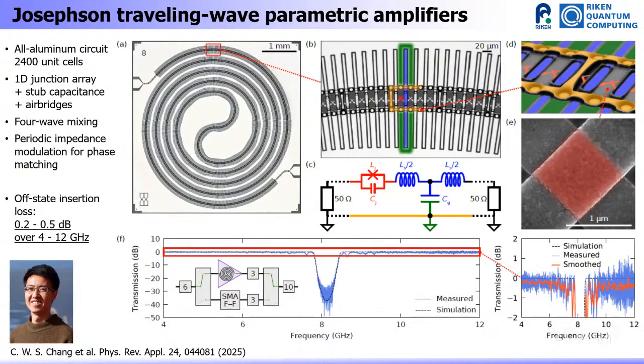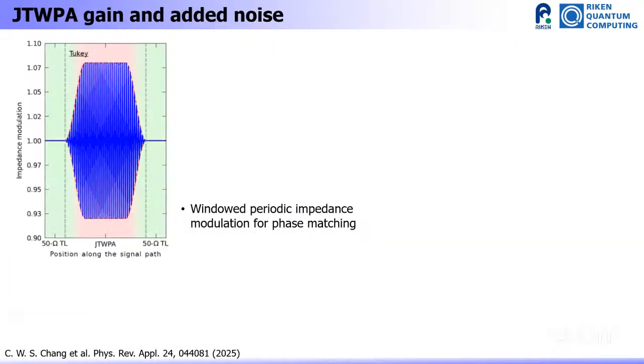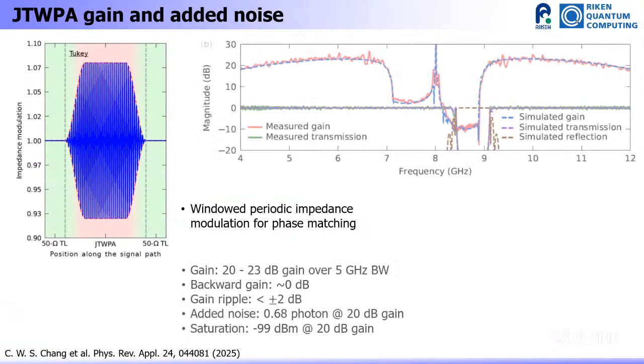As you see here, when we do not apply any pump, the transmission of microwave from 4 to 12 gigahertz gives at most 0.5 dB loss in the whole range. This part is the band gap because of the periodic modulation of this waveguide. When we input the pump power, we see a high gain of the signal microwave, above 20 dB, in a wide bandwidth of a few gigahertz at least.